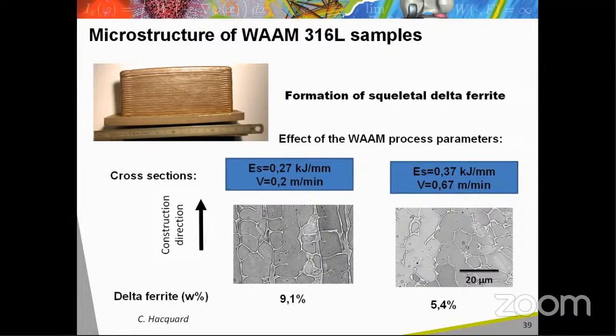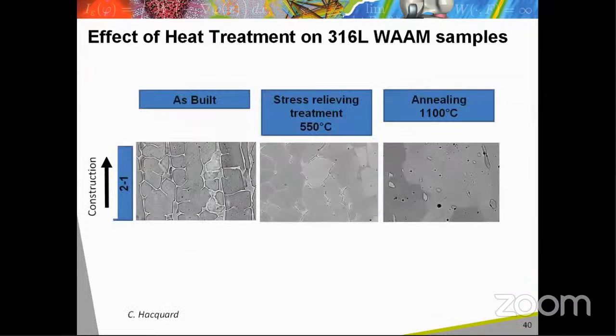The manufactured components in a 316L stainless steel can sometimes be used in an as-built state, but generally, heat treatments are applied on the components. These heat treatments can be stress release treatments at a temperature of about 550 degrees Celsius, or complete annealing treatments at a temperature of about 1100 degrees Celsius.